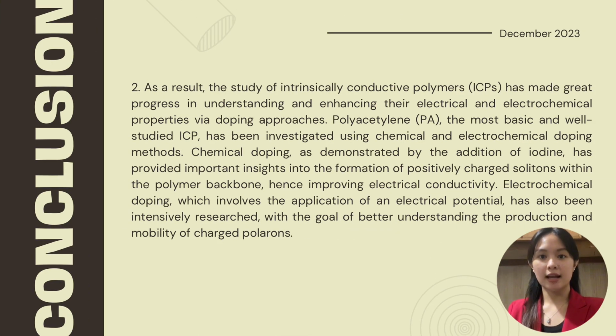Conclusion number 2. The study underscores significant advancement in enhancing the electrical and electrochemical properties of intrinsically conductive polymers, or ICPs, through doping approaches. Specifically, investigations into polyacetylene, a fundamental and extensively studied ICP, have revealed valuable insights through chemical doping, exemplified by iodine addition, elucidating the formation of positively charged solitons within the polymer backbone and subsequently improving electrical conductivity. Additionally, electrochemical doping involving the application of electrical potential has been extensively explored to gain a deeper understanding of the generation and mobility of charged polarons within these polymers.